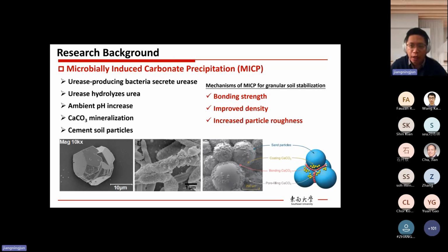Previous researchers on MICP have revealed that the mechanisms of MICP for granular soil improvement are mainly these 3 points. First, the generated calcium carbonate crystals could provide bonding strength, so it means that the cohesion could increase. Secondly, because we have extra crystals within the soil, the overall density of the soil is improved. Improved density normally means improved strength. And thirdly, some formed calcium carbonate precipitation could also coat the soil particles, so it could change the particle roughness, normally increasing it. This can also give additional contribution to the soil strength. So considering these 3 mechanisms, MICP is quite promising for granular soil stabilization.